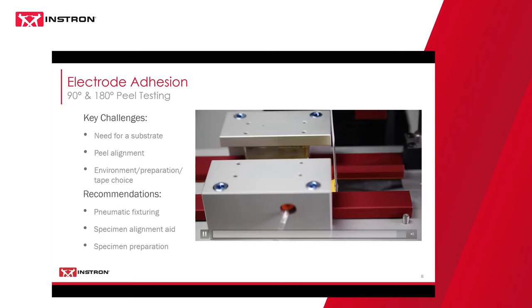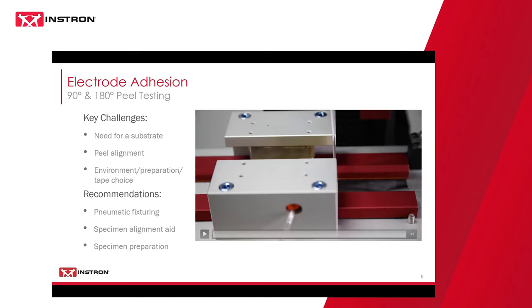Again, the pneumatic clamping is another thing: repeatable clamping force, ease of use, right? You don't need to manually clamp down on anything, which helps with your throughput. So if you're looking for the highest throughput for this type of testing, I highly recommend something like pneumatic 90-degree peel testing. If you're lower throughput and you're okay with the cleanup, 180-degree peel is also okay.